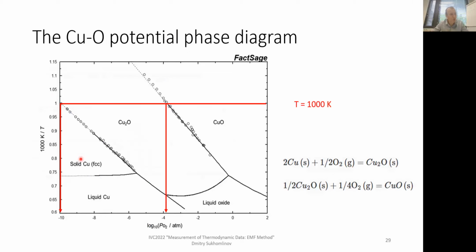And here I would like to again present a link to yesterday's lecture. So this is the same potential phase diagram for the copper-oxygen system we just discussed. And I would like just to show you how to read it. So for instance, we would like to know what is the equilibrium oxygen partial pressure when we have solid copper and Cu2O at 1000 K. So it's about 10 to minus 10. And when we have Cu2O and CuO, then it is around 10 to minus 4, slightly higher.